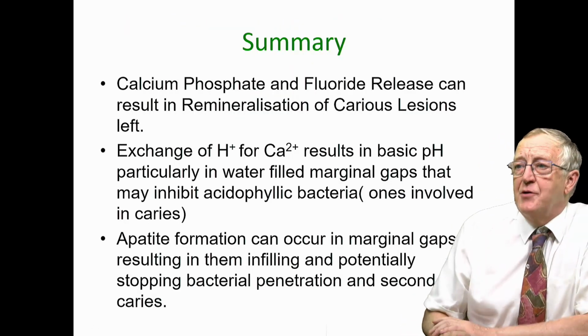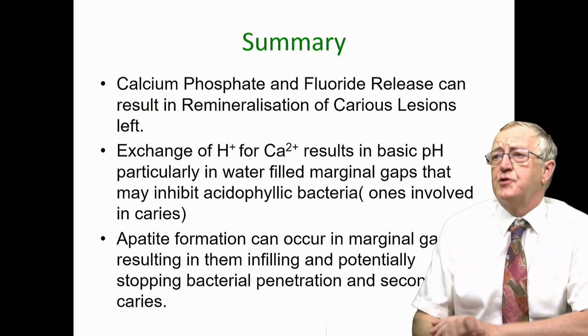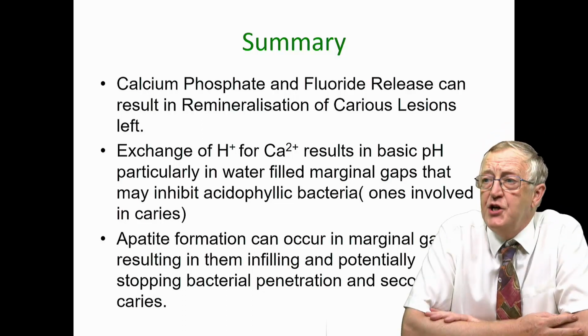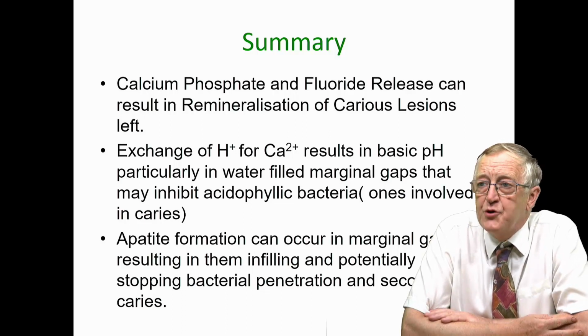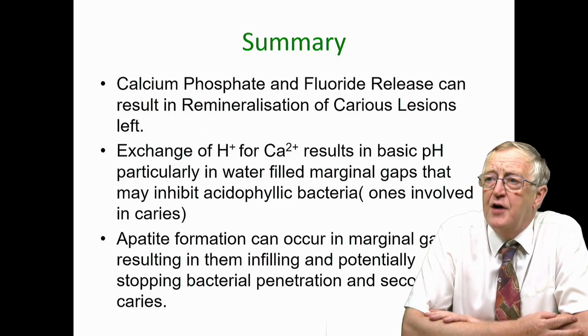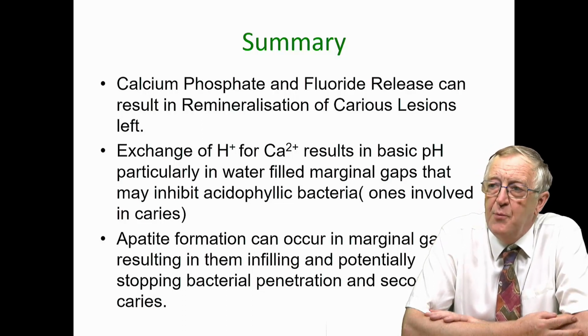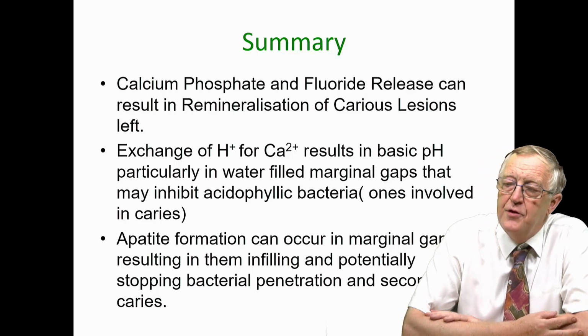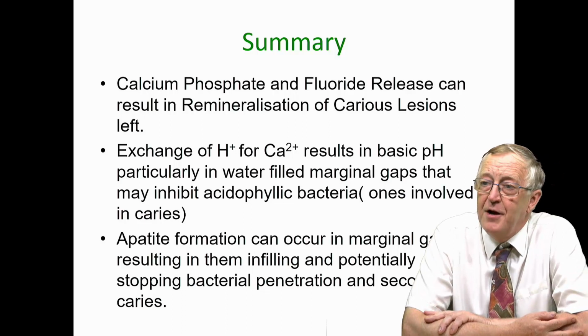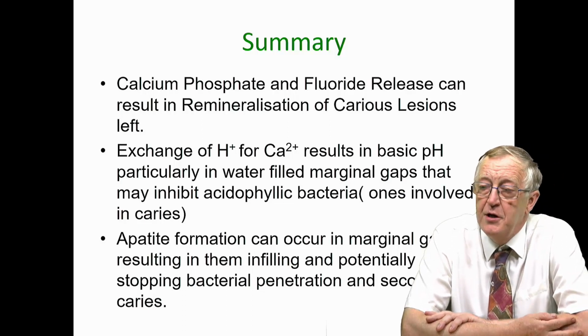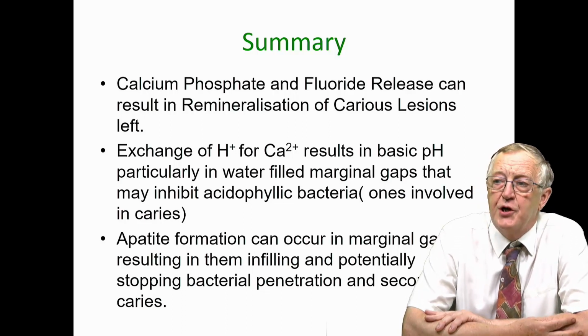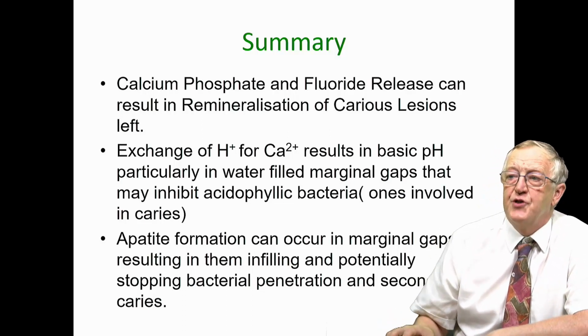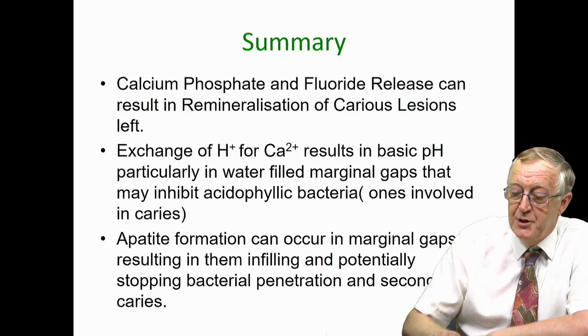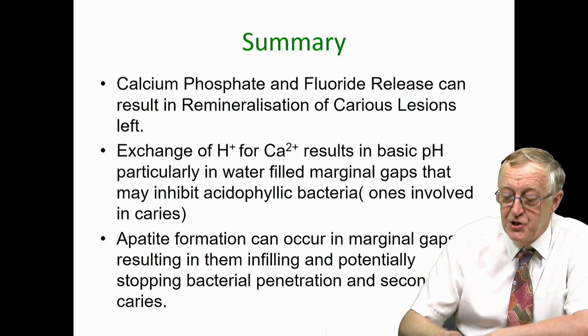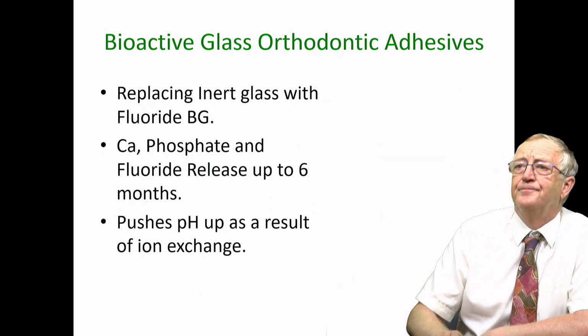So in summary, calcium and phosphate and fluoride release can result in remineralization of carious lesions left after ART procedures. The exchange of hydrogen ions and calcium ions results in a basic pH, particularly in water-filled marginal gaps, that may inhibit acidophilic bacteria, ones involved in caries. And apatite formation can occur in marginal gaps, resulting in them infilling and potentially stopping bacterial penetration and secondary caries.